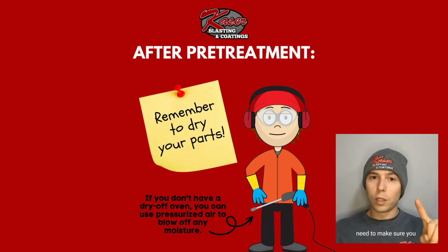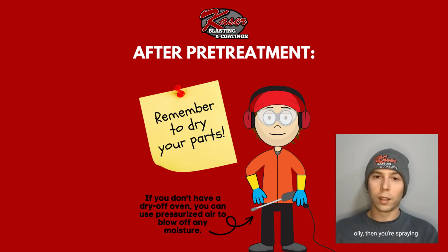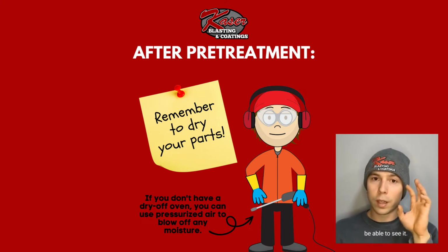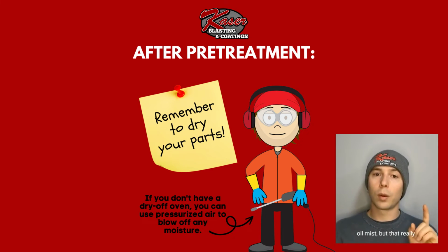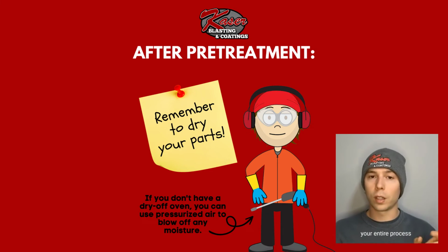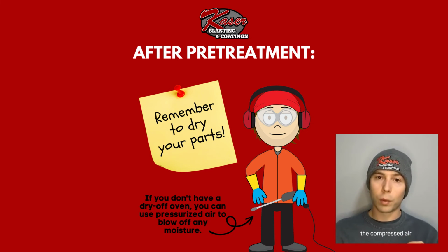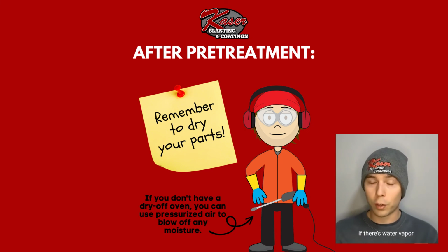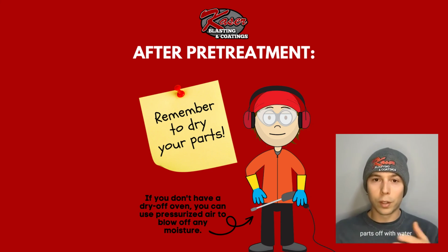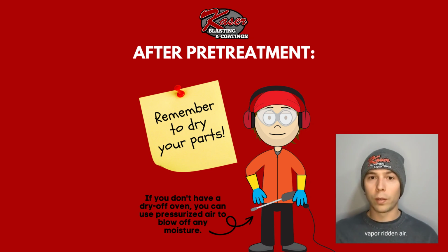The one thing that you need to make sure, you have to have clean air when you're doing this, because if you just cleaned and pre-treated a part and your air is oily, then you're just spraying the part with oil again. And you may not realize it, you might not be able to see it, it's more of maybe an oil mist, but that really can wreak havoc on your entire process if you're not paying attention to that. Drying the parts is really important, blowing them off with compressed air is really important, but the air needs to be clean and also dry. If there's water vapor in your air, then it does no good to blow parts off with water vapor ridden air.